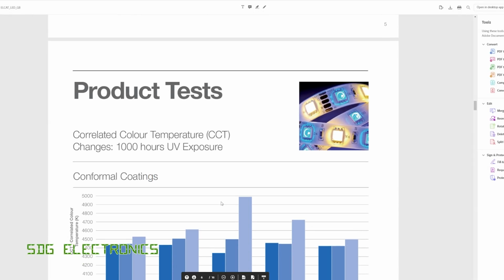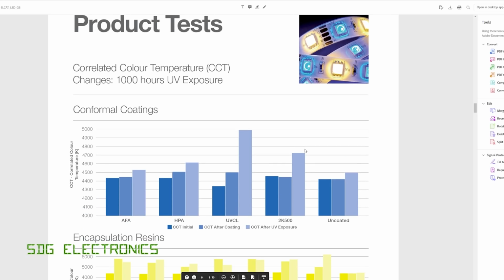Now, I did manage to find a datasheet from Electrolube about their various coatings that you can apply to LEDs. So firstly, as expected, the thickness of the coating affects the absorbance, but also the shift in color temperature. But it does look like no matter what you apply to these LEDs, there is going to be a shift in color temperature. It seems that all of these resins have some absorbance in that orangey red region that basically results in an increase in color temperature after you apply that conformal coating.